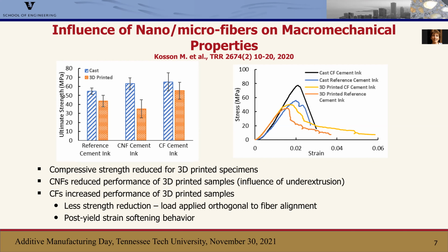Relative to the reference cement ink with the microfibers, we saw an increase in performance, both with an increase in ultimate failure strength, as well as interesting post-yield behaviors, where you can see in the image on the right, after it reaches that primary strength, rather than failing right away, we see what's called post-yield strain softening behavior, where the structure doesn't pop and fail, but rather fails gradually and less catastrophically.